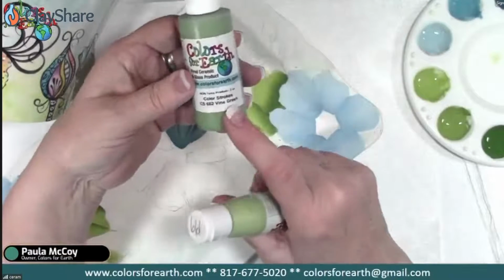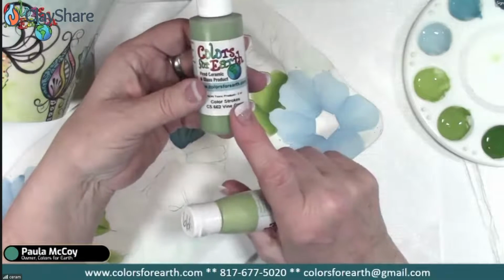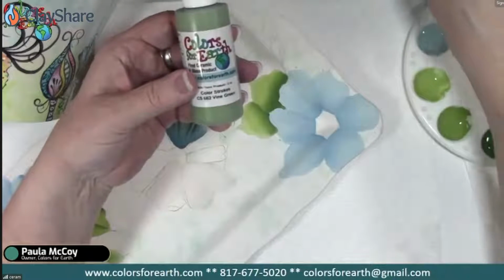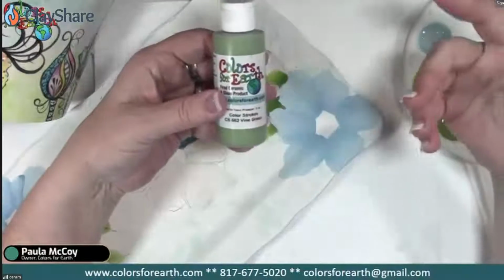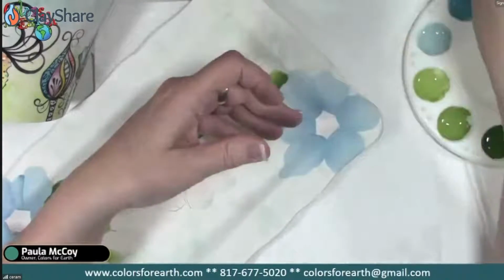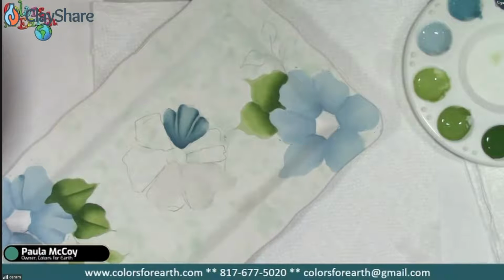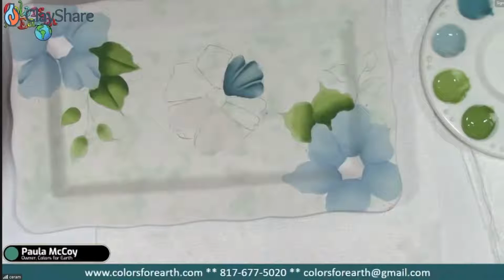So these are opaque underglazes, but they do need a clear glaze. They're not like stroke and coats. Stroke and coat is a glaze in a squeeze bottle. This is an underglaze, a true underglaze. So at the higher temps, cone 5, cone 6, sometimes depending on how heavy you put them on, they will gloss a little bit, but for them to be food safe, you have to put clear glaze over them. Okay. And my recommendation, either Jess's or, here lately, the Mayco SW-004 is the one I've heard good things about. Yeah, it works really well.